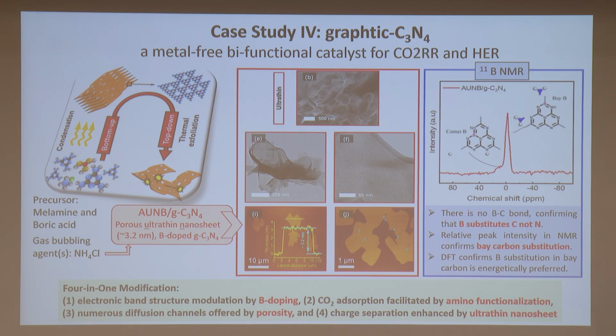The amino functionalization is very important in addition to the boron doping, because we can facilitate even more effective CO2 absorption. And the way we produce is highly porous. It increases the diffusion channels, okay? And the nanosheet, very thin sheet, we also accelerate the charge separation process. We call it 4-in-1 modification to make carbon nitride more useful. And of course, my student can play even further with more doping. So the co-doping of phosphor and boron, and also utilizing two bubbling agents to make it even more porous.